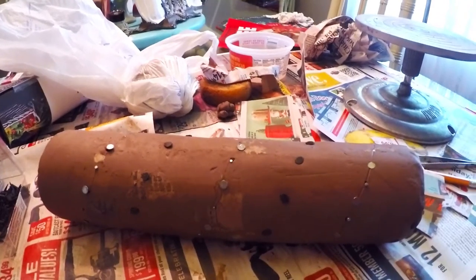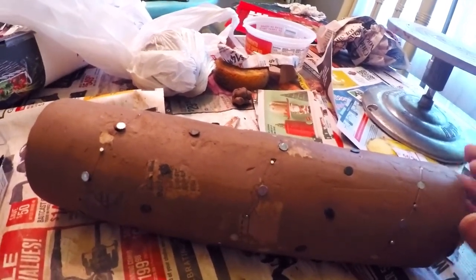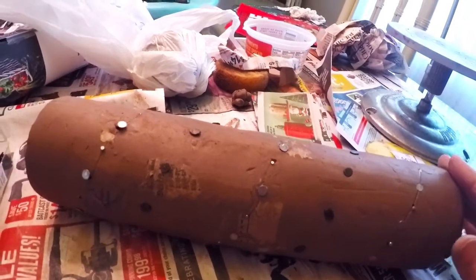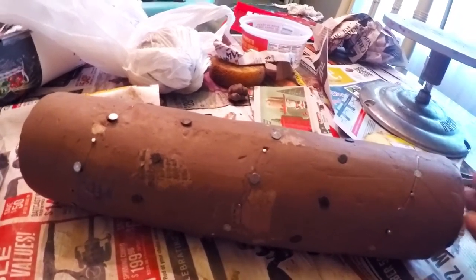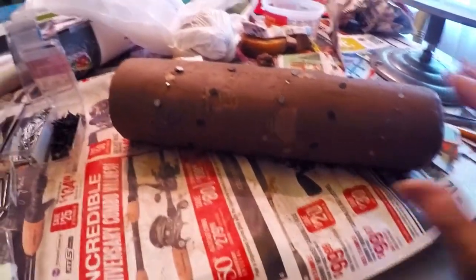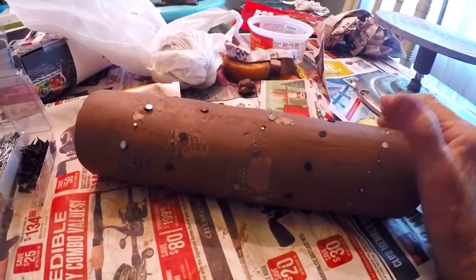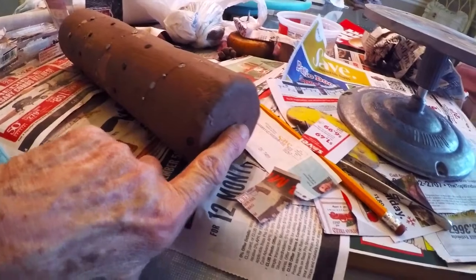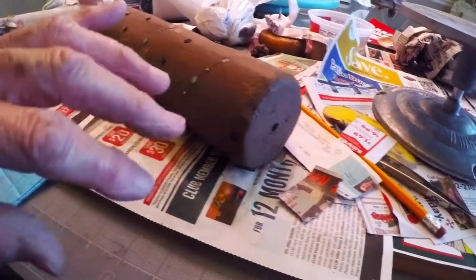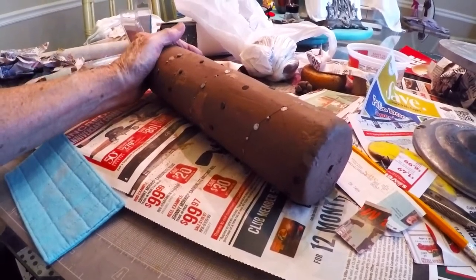Okay. Thanks for watching. I'll show you more of this when I'm done. I'm going to have to let it sit for about 2 weeks, considering the humidity around here, to dry, and then maybe even dry it a little bit in the kiln before I bisque fire it. I don't want it to explode. So don't rush the drying on these, teachers. The kids get real anxious, so put them out of their reach in the kiln room so that they can't mess with it in the meantime. But just make sure you have the hole in the end of it so that it'll be able to get rid of the ash and also the steam as it's firing.